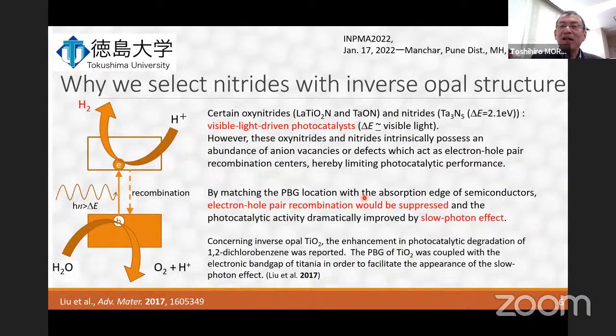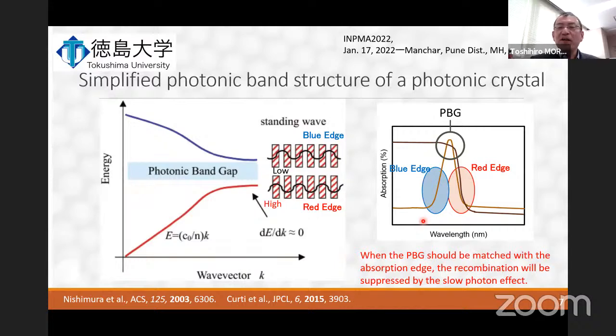Certain oxynitrides and nitrides are known as visible light photocatalysts, as you know. However, these oxynitrides intrinsically possess an abundance of anion vacancy defects, which act as electron hole pair recombination centers. Hereby, these defects limit the photocatalytic performance. But by matching the PBG energy with the absorption edge of semiconductors, electron hole pair recombination would be suppressed, and the photocatalytic activity dramatically improved by the slow photon effect. I'll explain the slow photon effect later. This figure represents a schematic drawing of the simplified photonic band structure.